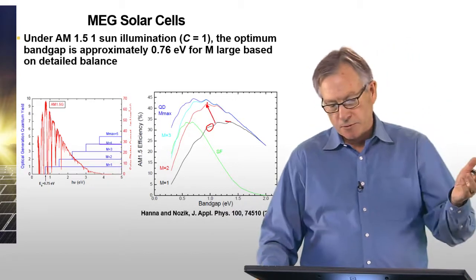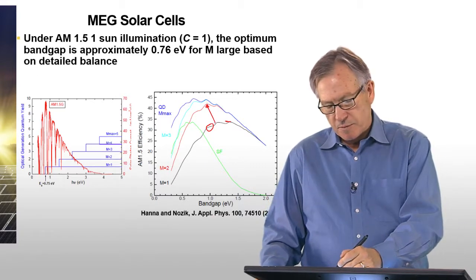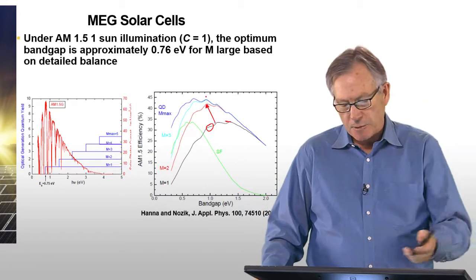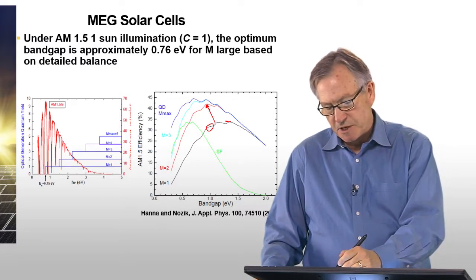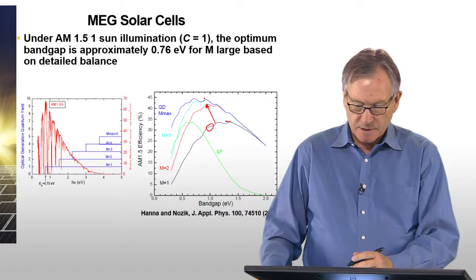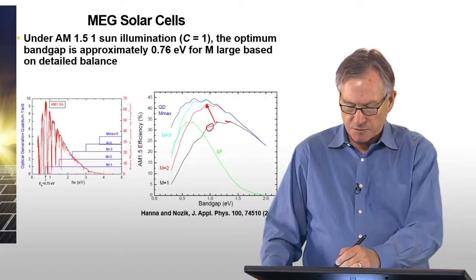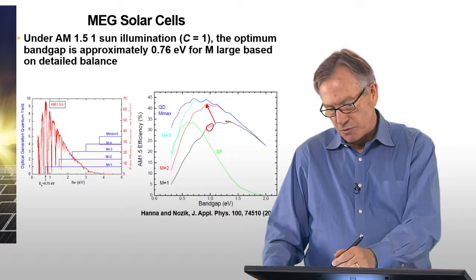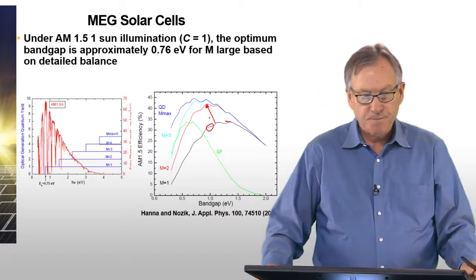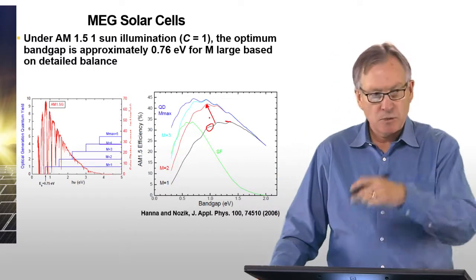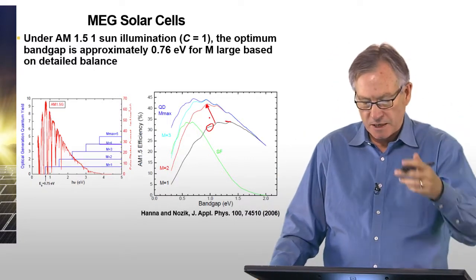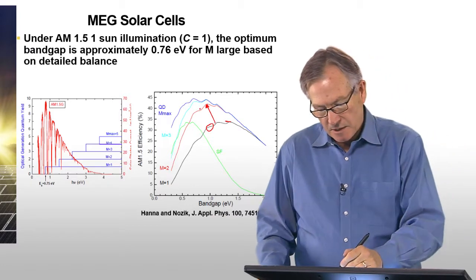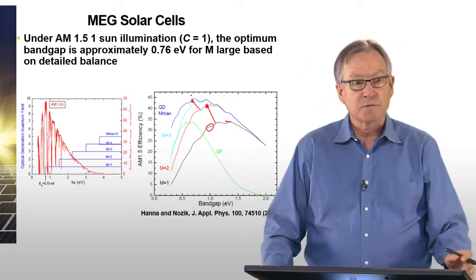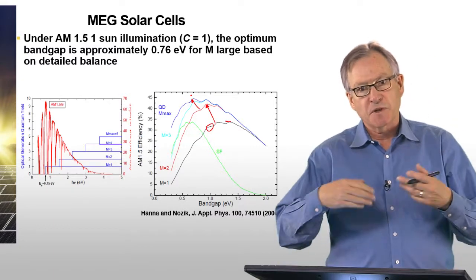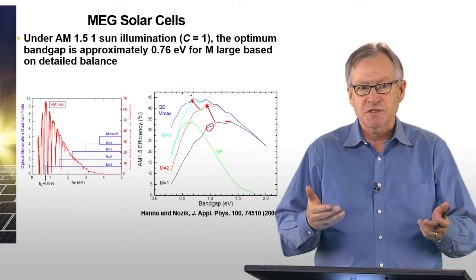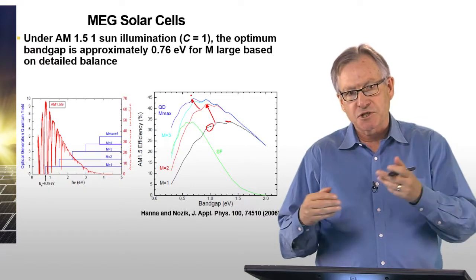So simply by including the possible effect of creating a second carrier by high energy photons, the maximum efficiency immediately jumps from 33.7% to over 40%. And notice also that the band gap shifts lower. Instead of being between 1.1 or 1.2 and 1.4, it's now shifted down to about 1 eV. And if you allow multi-exciton generation to occur at 3 times the band gap and 4 times the band gap, the efficiency can go even higher, closer to 45%. So this is of interest in improving the efficiency of even conventional solar cells like silicon, if one could introduce multi-exciton generation into silicon.